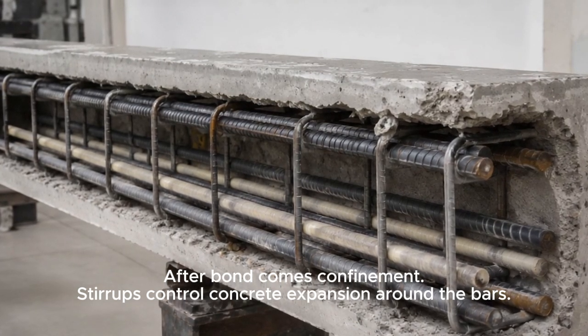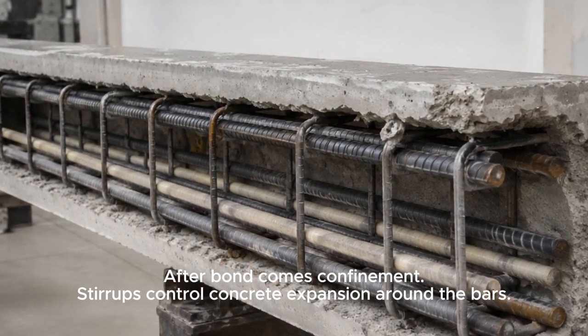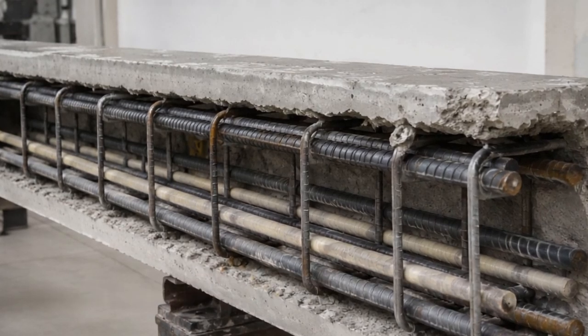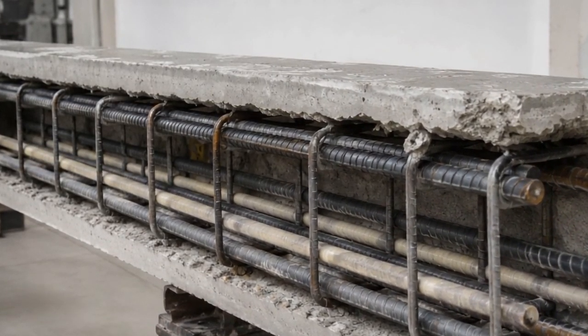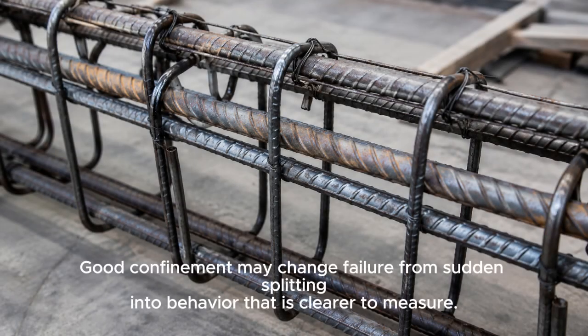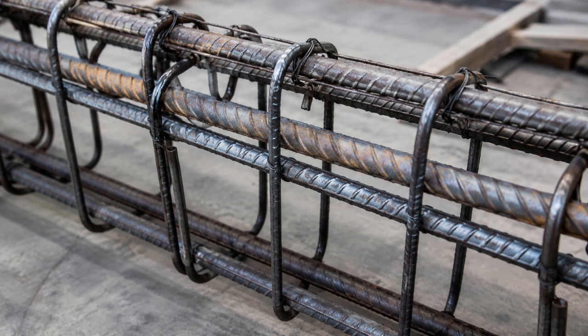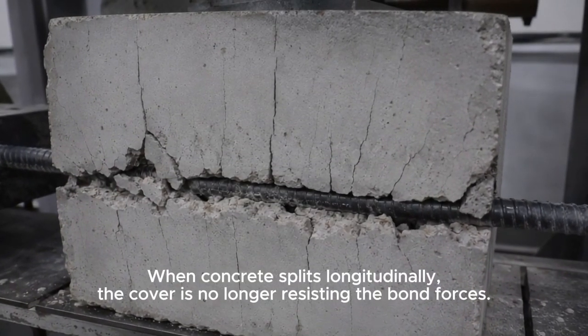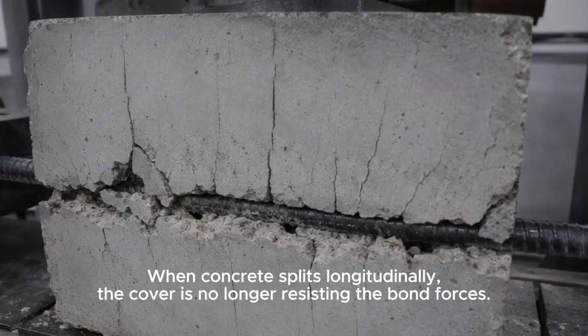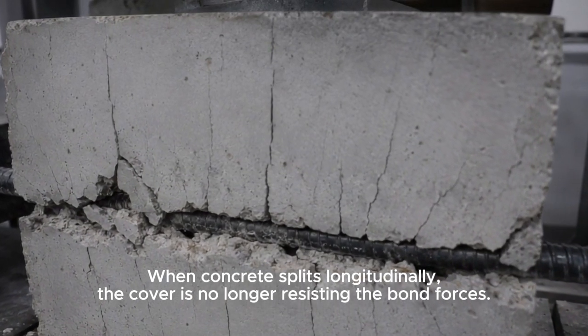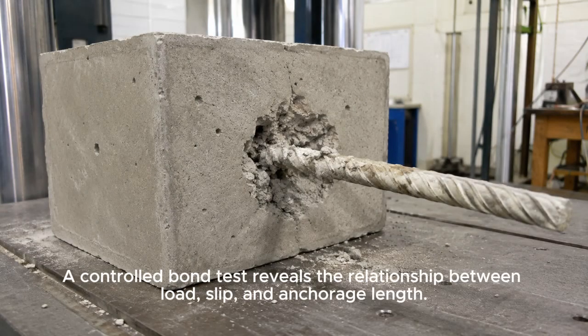After bond comes confinement. Stirrups control concrete expansion around the bars. Good confinement may change failure from sudden splitting into behavior that is clearer to measure. When concrete splits longitudinally, the cover is no longer resisting the bond forces. A controlled bond test reveals the relationship between load, slip, and anchorage length.